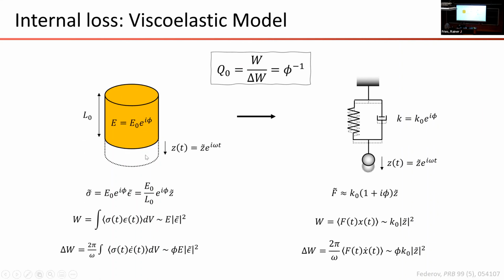So in continuum mechanics, the way you would model this is, say you have some elastic body that's being deformed sinusoidally at some frequency. What the viscoelastic model of internal loss would look like is that you introduce a complex elastic modulus to represent the fact that changing the dimensions produces some stress. That stress is out of phase with the strain.